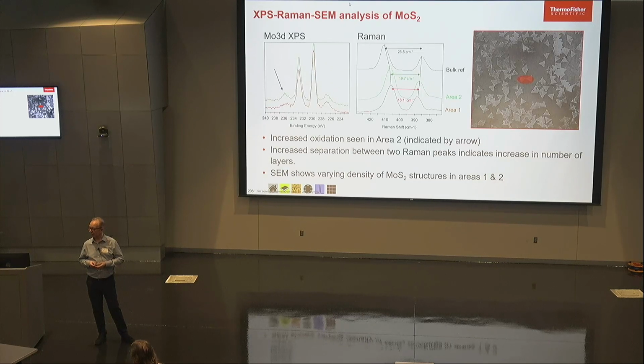Yeah, that's a good point, Dan. So you can also, on instruments that don't have the low vacuum approach, use beam deceleration. So you can run at a low voltage and then actually bias the stage. So you slow the electron beam down so that you can image samples there as well. So, certainly for looking at insulators, the way that microscopy technology has moved on over the past sort of decade or so has been a real help, particularly if you want to correlate your data with a surface analysis system.